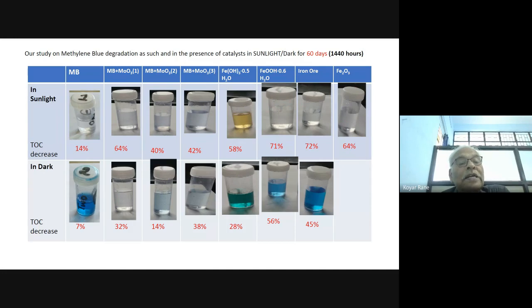Normally in the literature, we study the methylene blue degradation for 24 hours, then study the kinetics and all those things. Then we say that our catalyst is the best one. But in fact, the organic matter is still there in the methylene blue. In the dark, you can see just 7% organic matter is removed.